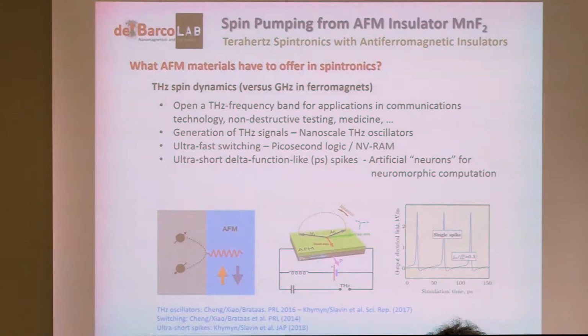It's not just the anisotropy that plays the main role in ferromagnets, driving ferromagnetic dynamics into the gigahertz, maybe tens of gigahertz. But here we have the combination of the magnetic anisotropy with the exchange interaction between the sublattices that amplifies the frequency of those dynamics by at least two orders of magnitude, driving this into the terahertz. Well, if we take this into account and we can employ this in the way that it has been done with ferromagnets, one can think about generating terahertz signals by